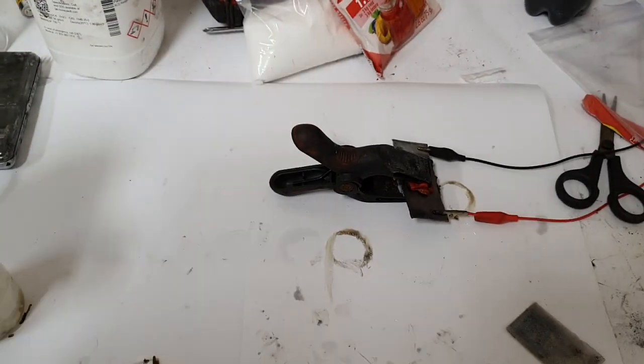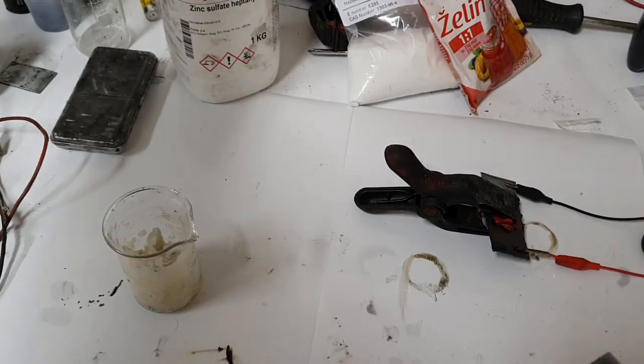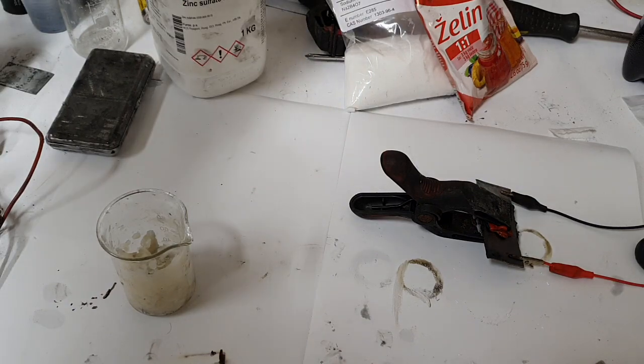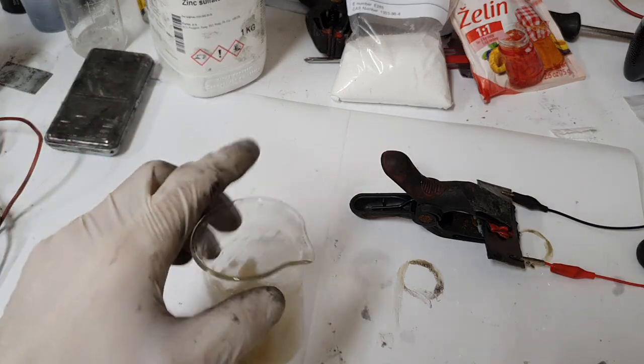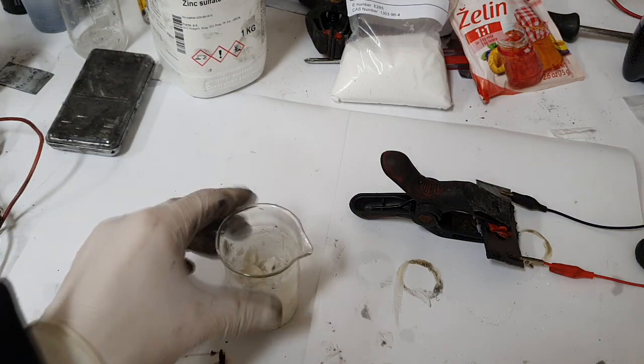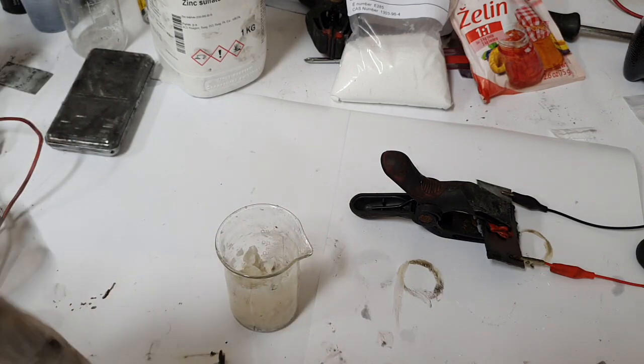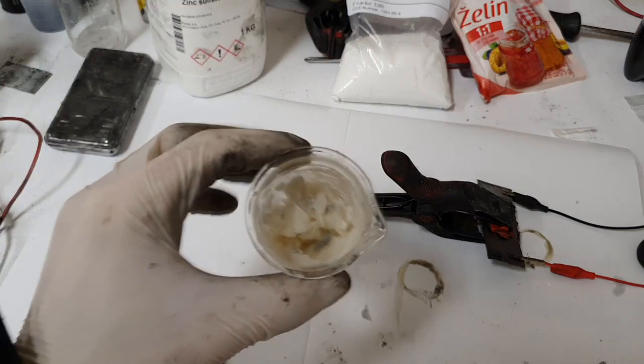So basically, here is how to make this: in the first beaker you add 30 ml water and 23 grams of zinc sulfate. In another beaker you add 4 grams of gelatin and 4 grams of borax into 30 ml of water, but the water needs to be hot at 80 degrees C and you need to stir when you add the borax and gelatin. When the solution is at 80 degrees C, you add the zinc sulfate solution.